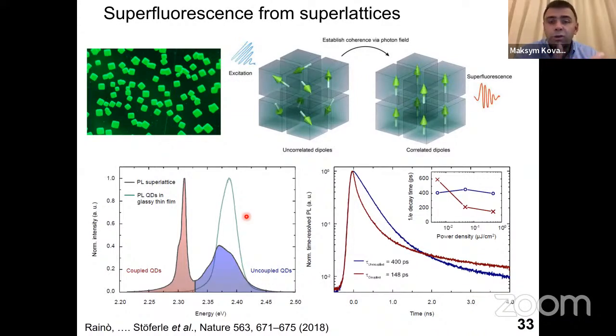And this is a coupling, incoherent coupling, of these entities. And then as you start increasing the power density for your excitation, you start seeing the shortening of the radiative rate without losing the quantum efficiency, which means that you have pure acceleration of emission. So what happens is that your initially incoherently excited quantum dots build coherence across themselves if they are in sufficiently close proximity. And for this effect, they have to be within something like half a wavelength from each other. So if in that volume you have a sufficient number of photo-excited quantum dots, they start building coherence across themselves and establish large multi-particle dipoles, which emit coherently, and which emit light with a faster radiative rate because they have a higher oscillator strength.